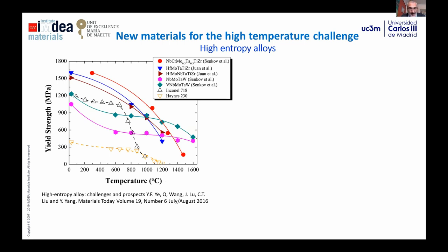we are finding a lot of new materials. One new material that has been developed in the last, let's say, 10 years is high entropy alloys. In high entropy alloys, if you see the correlation between the yield strength and the temperature, this is a material that can compete with good advantages with conventional Inconel or other nickel-based superalloys, which we have here, the behavior against the temperature. Here we have the new high entropy alloys. So we have moved the curves in this way, in which we have much better behavior with the temperature.